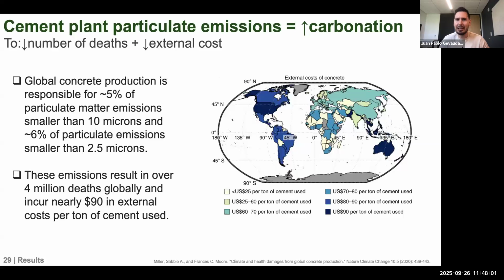So we really need to be thinking about solutions that are addressing not only the carbon intensity, the CO2, but also looking at other emissions that are problematic in the cement industry. What we think here, though, is that by including particulate emissions in our technology, as well as CO2, we can create a synergistic opportunity where the cement particulate emissions increase the pH. Those allow us to increase the rate of carbon sequestration.